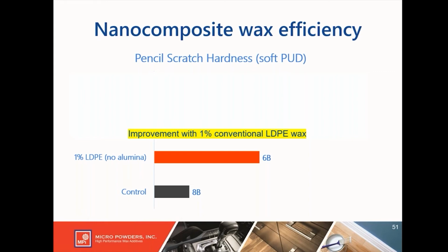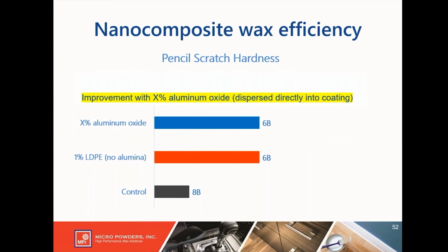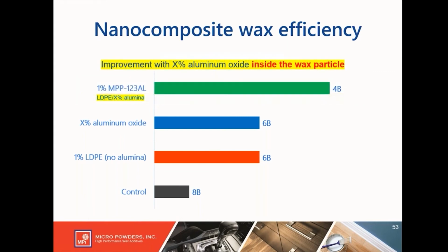1% of low-density polyethylene powder, we improve the scratch to a 6B. If we directly dose X% of free aluminum oxide into the coating, we also get a 6B performance. However, if we take that X% of aluminum oxide and put it inside a wax particle, so we're dosing 1% of MPP 123AL at the top, which contains X% of aluminum oxide, look at the improvement in performance. So the blue and the green bars, the formula contains the same amount of aluminum oxide, but in the green bar, the aluminum oxide is in a buoyant wax particle, getting to the surface more efficiently, giving you better performance, better scratch resistance. Particles not at the surface are wasted.